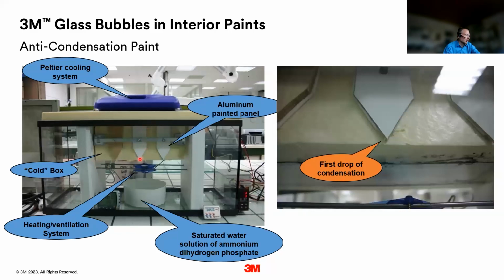The samples are actually again aluminum panels, here in the form of this arrow, and these panels are again coated with different paints with different formulations. So the samples are in an atmosphere of high humidity, and there's a cooling from the back. Then we watched until condensation forms, first drops are formed and finally drop off, and we measured the time until that happens.